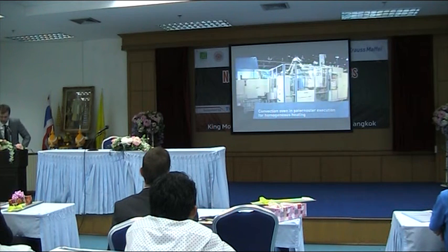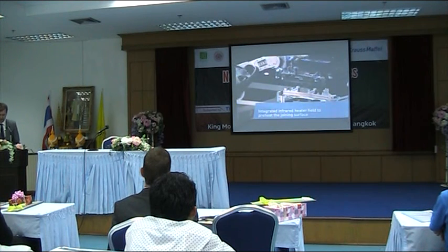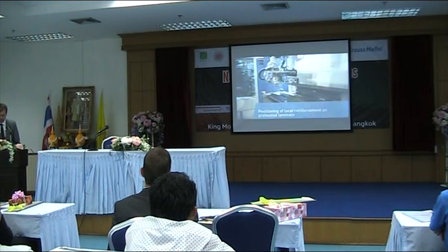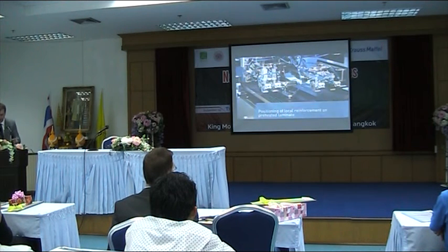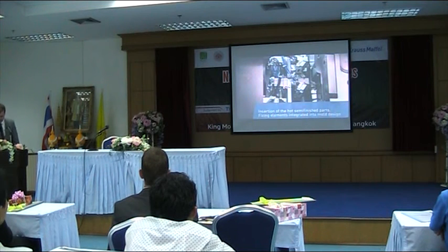It's heated up in a convection oven. You also have infrared temperature monitoring, and also an infrared heater field to reheat the surface. The local reinforcement is placed on the preheated laminate. And we have a special heat equipment, and the second is also an advantage.